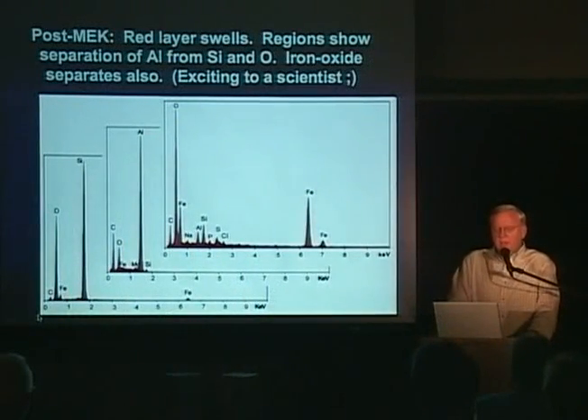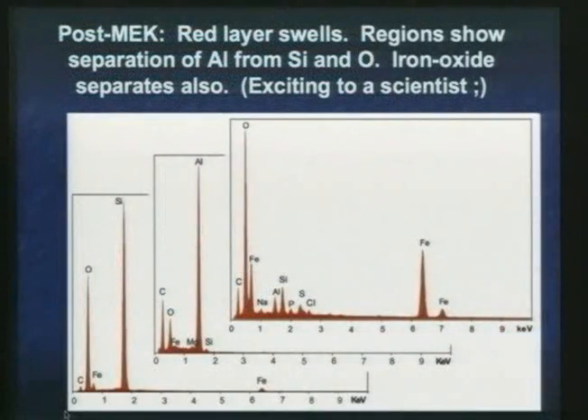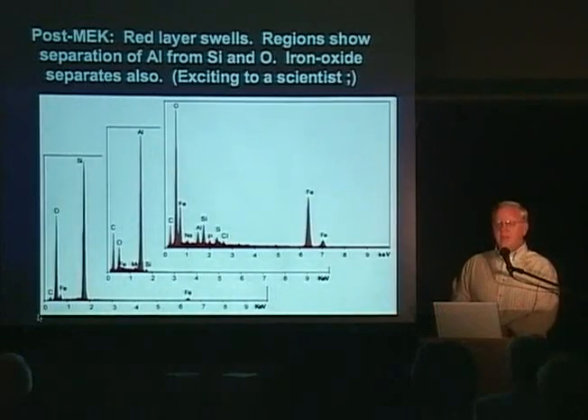Okay, let's look at the data. Getting ahead of myself. This is in the paper. After the MEK soak, we now see regions where we see aluminum separated from silicon and oxygen. If you look at the leftmost plot, you see the silicon and oxygen, a little bit of iron, essentially no aluminum. This is not aluminum silicate. It's not kaolinite, as some debunkers said. Oh, it's kaolinite, that's all it is. No, you can't use a paint solvent and separate the aluminum from the silicon oxide in an aluminosilicate. It's just a solvent. It's not a reducing agent, okay?